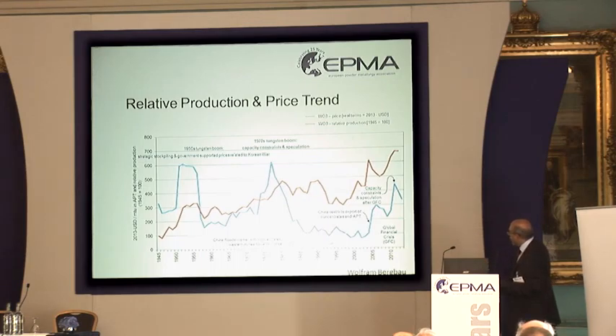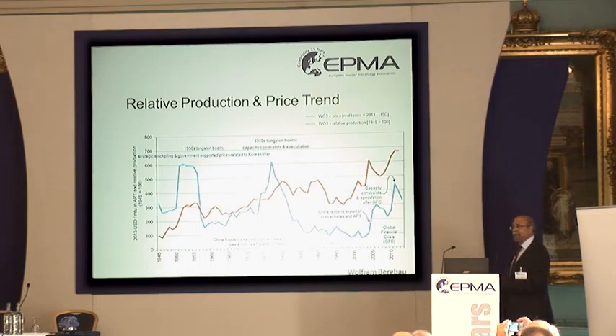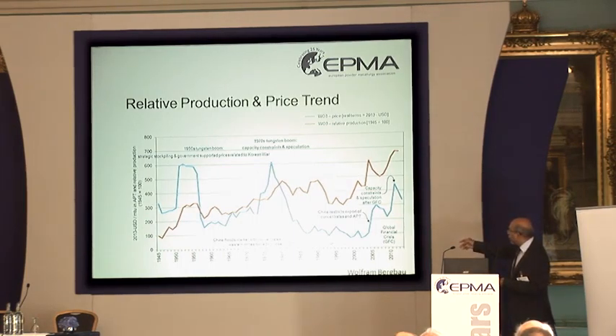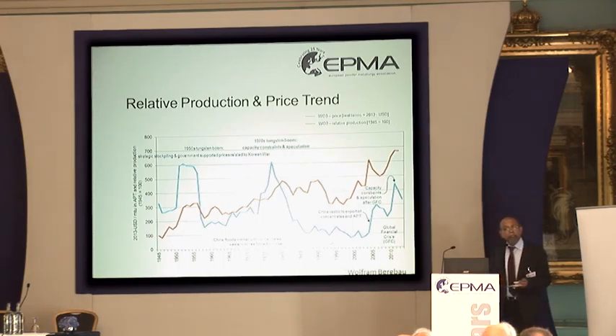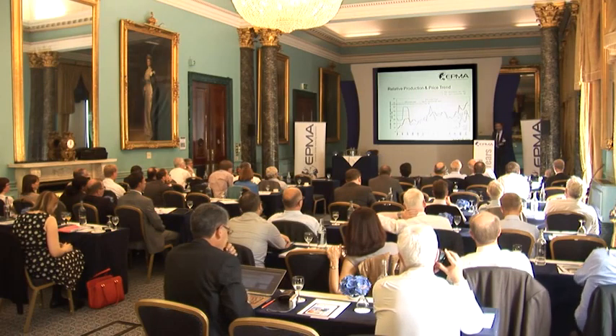And in 2005, the Chinese decided that they have full control of the tungsten market. Hong Kong was closed to free trading and for smuggling. Before that, we could get anything we wanted through Hong Kong. And they just put on the screws, and we have been suffering. The prices, within 1 year, went up by 3 to 5 times, depending on where you bought your powder. Even today, the powder is much more expensive, and if you buy the same powder in China, it's about 30% cheaper compared to the price you pay in Europe.